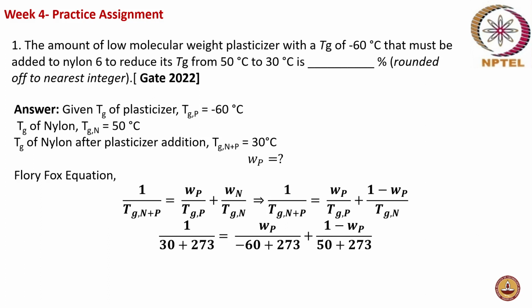So it will be 1 by 30 plus 273, right? And similarly minus 60 plus 273, 50 plus 273. So 1 by 303 is equal to weight fraction of plasticizer by 213 plus 1 minus weight fraction of plasticizer by 323. So that will end up with a weight fraction of the plasticizer to be 0.1278, which is nothing but 12.78%. So if you add 12.78%, approximately 13% of the plasticizer, the glass transition temperature of the nylon gets reduced from 50 to 30 degrees. Are you able to understand?